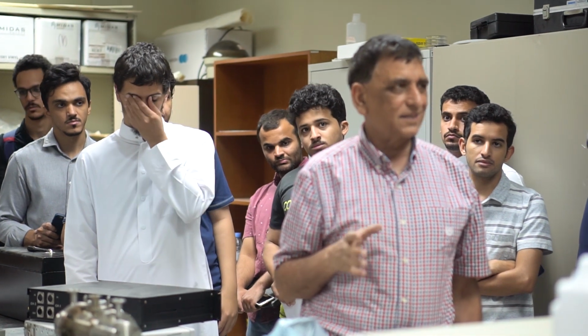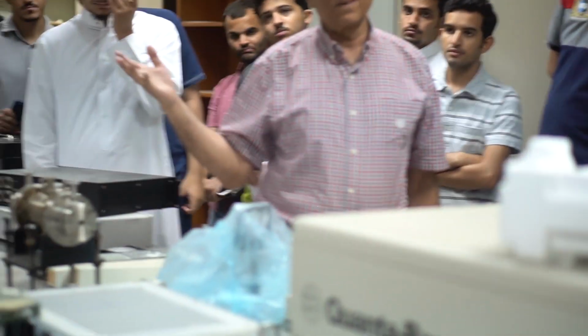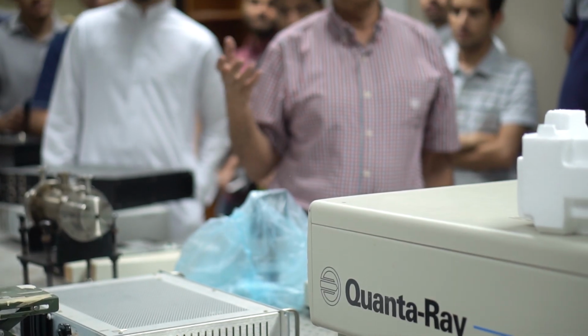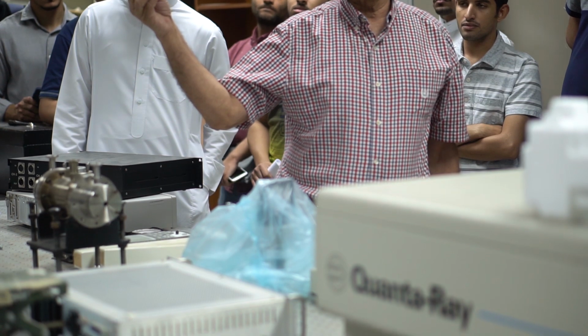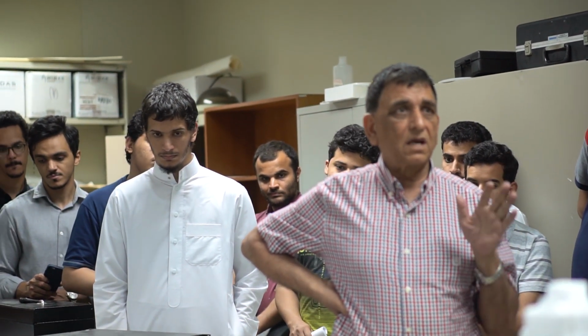So now let's say I have a target of zinc and I put some oxygen gas in my chamber, where I have a 10 to the minus 7 vacuum. I introduce very little oxygen, so I can make a film of zinc oxide, Zn plus oxygen. I break oxygen O2 into atomic oxygen. This atomic oxygen is very reactive. So when very small particles of zinc come through by ablation, they catch oxygen and make ZnO on the substrate. So I can make many materials like this, very clean. And this technique we call pulsed laser deposition.